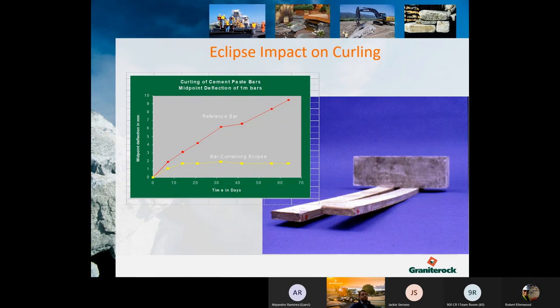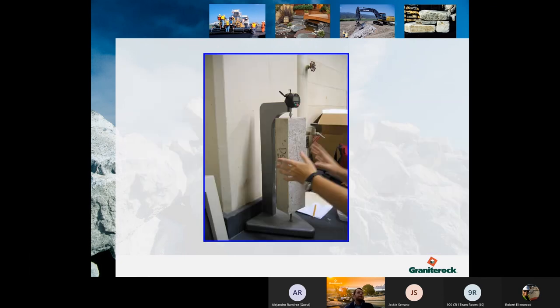Here's another example of a good application. Like I was talking about topping slabs, this is a good use for Eclipse. Because the concrete's not shrinking or pulling on itself, it decreases the amount of curling. And when you're pouring a thin slab on top of other concrete, it really has nowhere else to go, so it'll curl. By using Eclipse, it can help mitigate that. Here is a shrinkage bar. These are made from concrete and they are cured for 7 days and allowed to dry for 28 days after that. Every 7 days, it's placed in this machine here where it records the length of the bar.